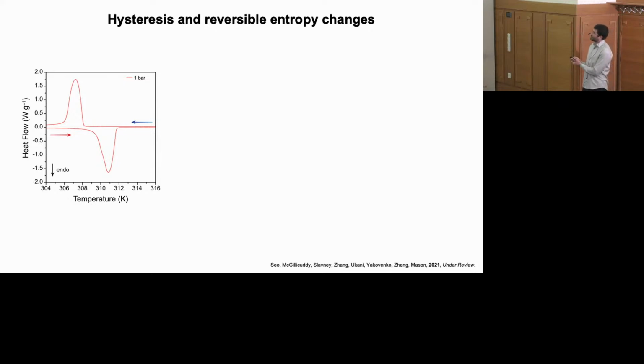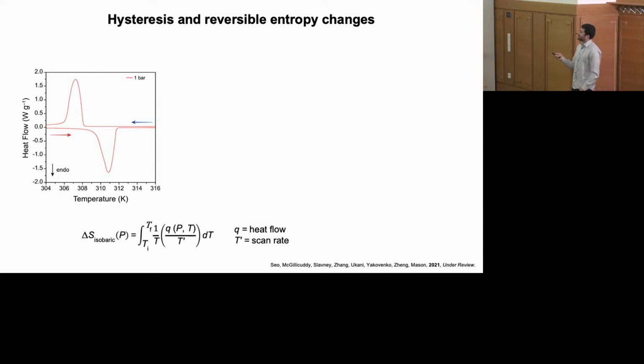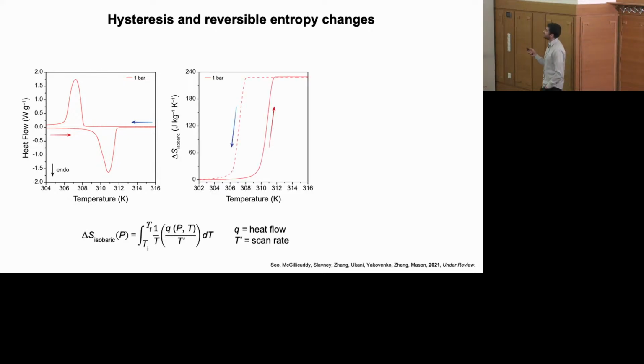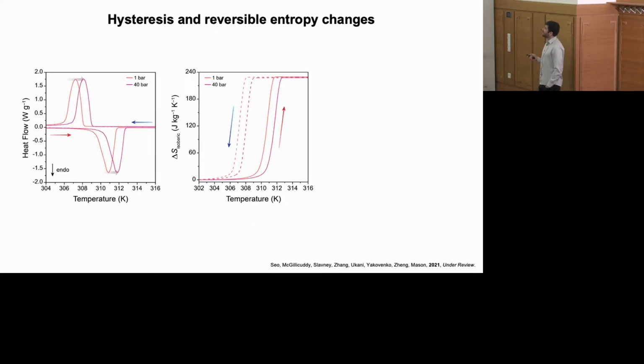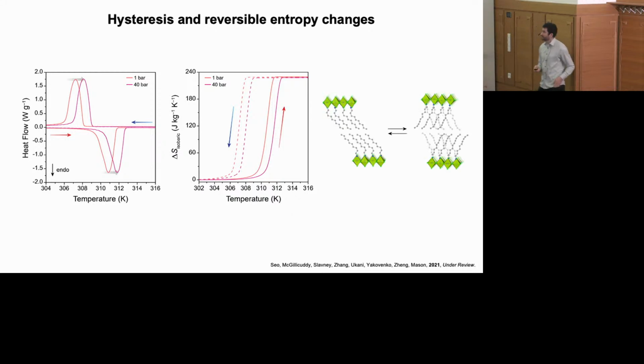So the experiments we do are isobaric, meaning they're done at constant pressure. But what we'd like to do is get information about what will happen under a constant temperature environment. So we can convert this raw heat flow data to entropy data, entropy as a function of temperature. And we can calculate the change in entropy for different pressures. So here all we're saying is that we start at the low entropy ordered state of our material. As we increase temperature, we undergo the phase transition to the disordered state. And the temperature at which this happens increases as we increase pressure.